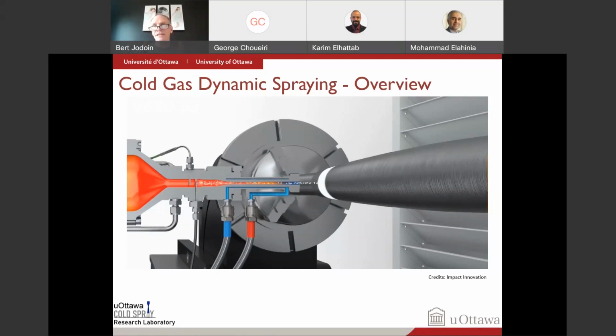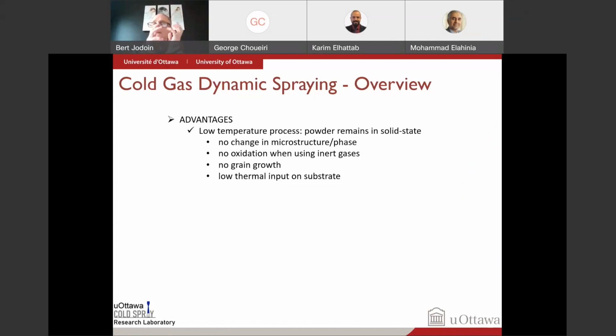So you inject a material that has a little bit of ductility, mostly metals, and then you can get coatings out of them. So the advantages of this process, the main one, it's a low temperature process. Even though we can preheat the gas up to 1,000 Celsius, it expands in the nozzle, so it quickly drops below room temperature. So that means our tiny solid particles do stay in the solid state. So that's quite interesting because it means there's no change in the microstructure or phase because we don't have melting. There's no oxidation because we're using inert gases such as nitrogen or helium. If you start with a powder that has nanograins, well, you don't get grain growth because it's at low temperature. And it's very low thermal input on the part that you want to coat. So that will prevent distortion or thermal distortion.